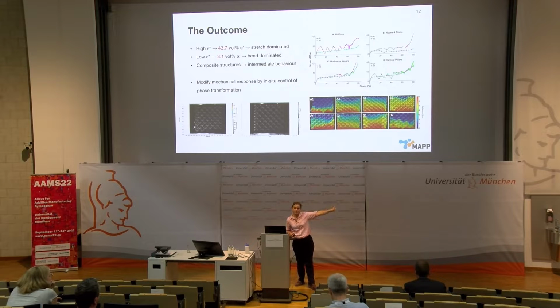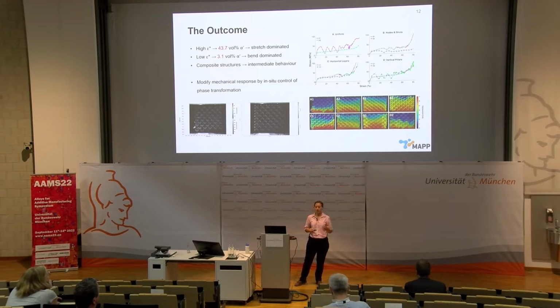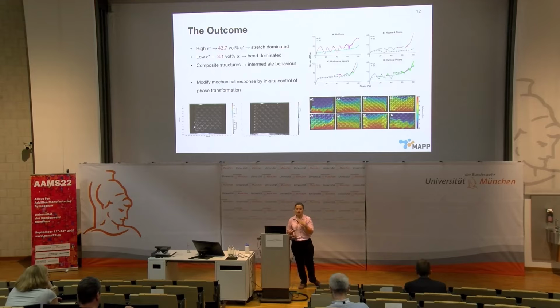So the set of coloured images in the bottom corner there are differential image contrast. They're all taken at around the same level of deformation, and we can see displacement patterns on there. So we're looking at moving where the displacement is taken up, how it moves through the material, which bit of the material is failing first. And that gives us confidence that we can then take this technique and go on with it to look at producing more damage-tolerant structures which have a more tailored level of control, and with this, potentially also expanding that out to look at other material systems that exhibit phase transformations. Because if we can do this with one material, it should be possible to open it up and do it with other materials as well.